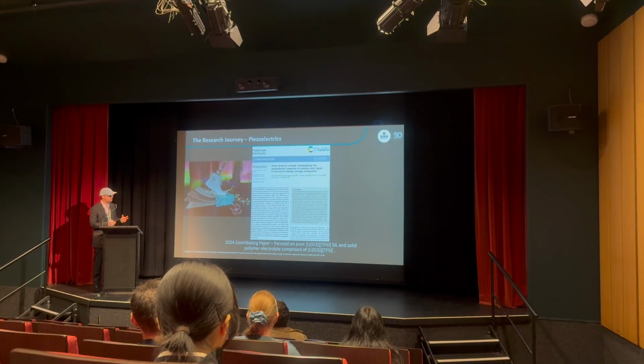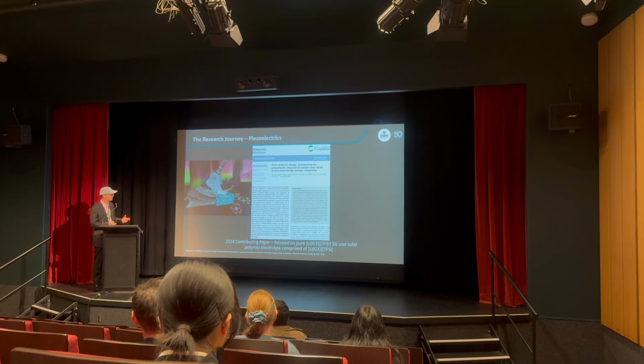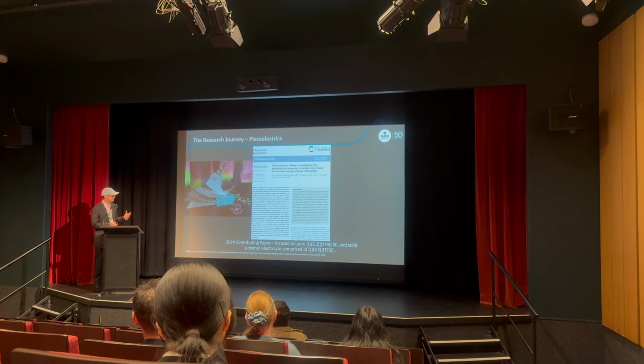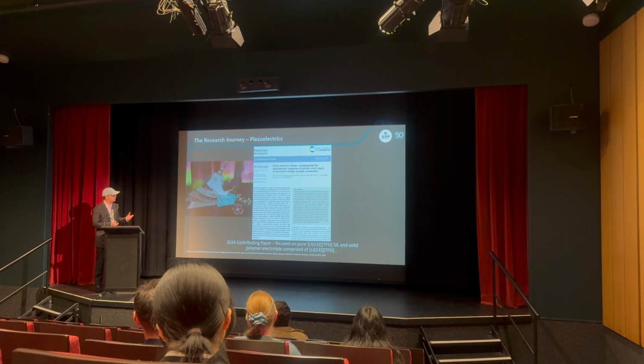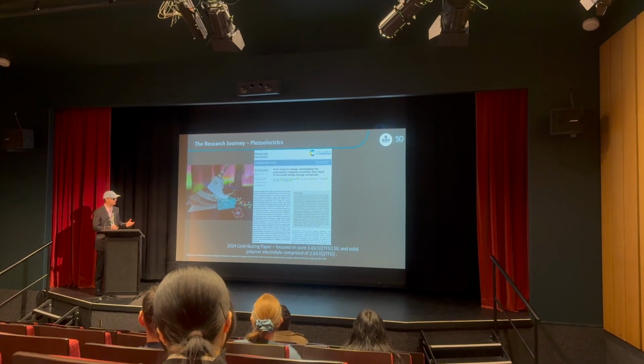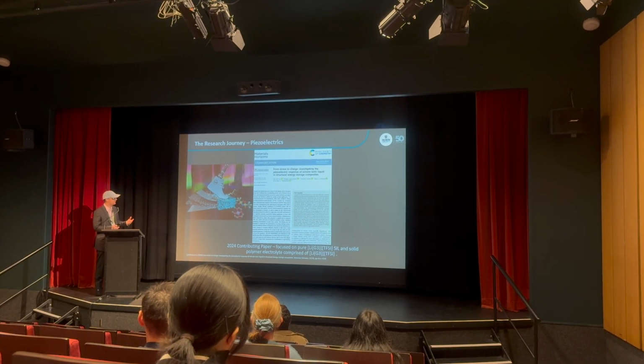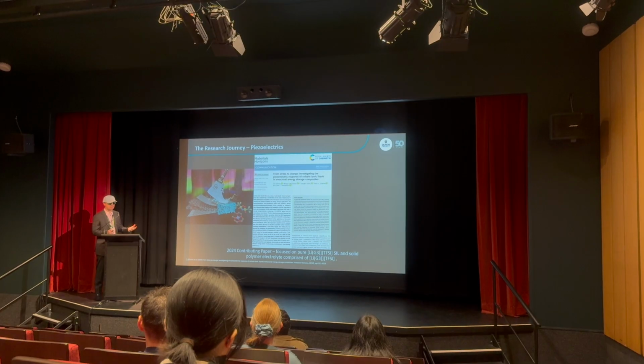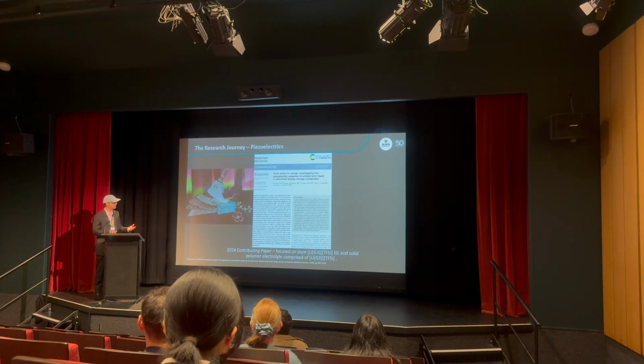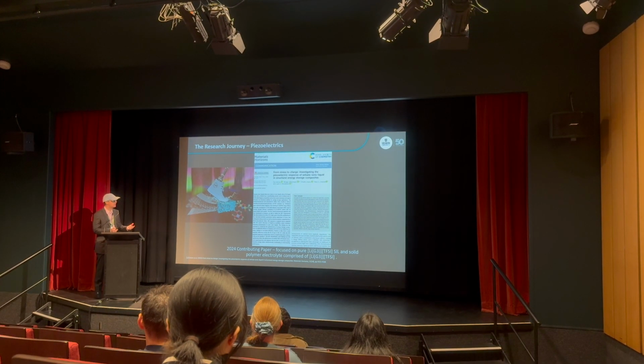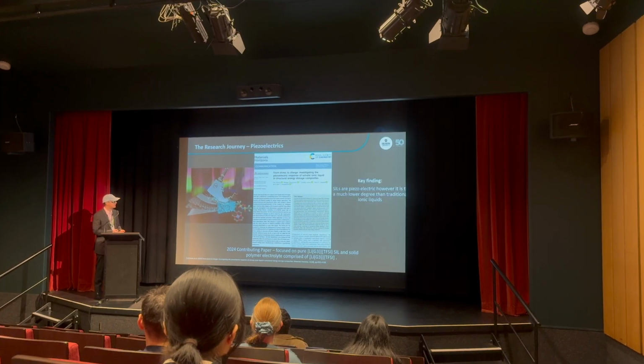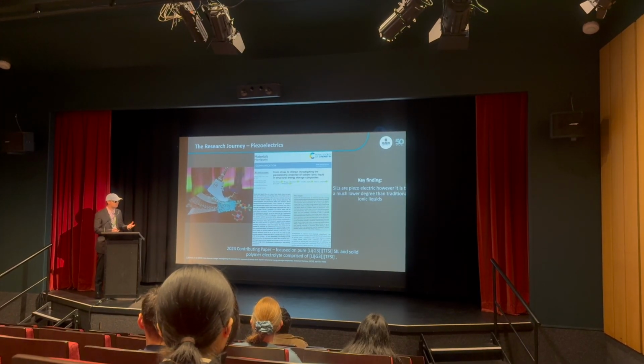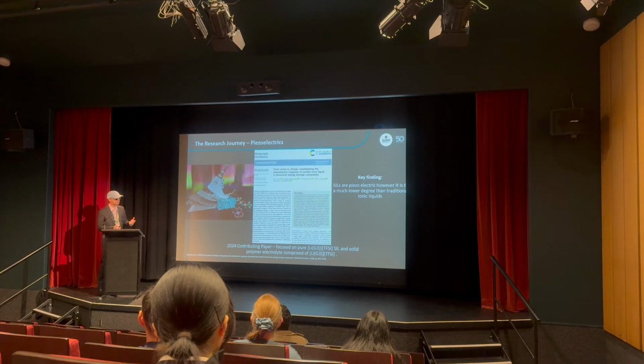So coming to the topic of my talk, which is piezoelectrics. Traditional ionic liquids were shown in the literature around 4 to 5 years ago as being piezoelectric. We were curious whether Solvate Ionic liquids were. We didn't really have the equipment to do D33 testing, which is piezoelectric coefficient testing, so we set up on the load frame Instron and did it ourselves using an open circuit potential. And we showed that Solvate Ionic liquids are piezoelectric, however it is to a much lower degree than traditional ionic